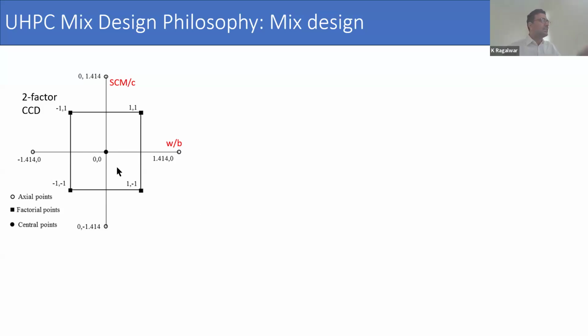That process is fed into what is known as an experimental design. Here SCM is any kind of supplementary cementitious material such as silica fume or slag or fly ash. So rather than conducting an abundant number of tests, we came up with a philosophy where we can conduct 9 points. These are 4 plus 4, 9 points on a plot, which is water to binder ratio and supplementary cementitious material to cement ratio. And then 4 additional experiments are conducted at the central point.